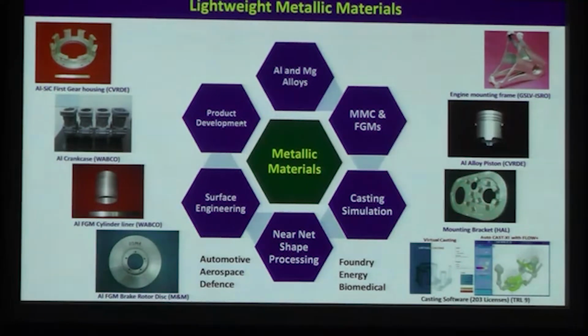At the other end, we can see the aluminum SiC first gear housings, again for lightweight compact battle tanks. And it is, again, for CVRDE. The main requirement here is high wear resistance with high stiffness. So by incorporating silicon carbide particles into aluminum, we are able to make these first gear housings.